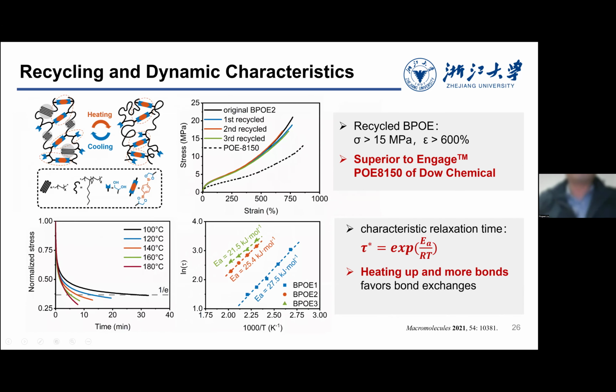And the interesting thing is, even though they have been chemically cross-linked, they can still be reprocessed. For example, we did 3 reprocessing cycles of these cross-linked BPOEs, and they still show good performance. You can see here, this is the first, second, and third recycled. Their tensile curves still almost repeat each other. And this performance is still superior to Engage POE 8150 of Dow Chemical.